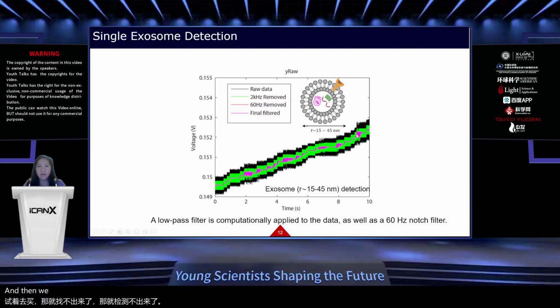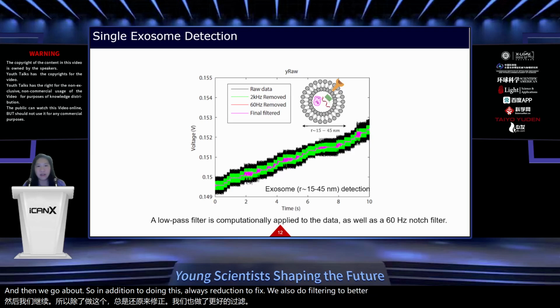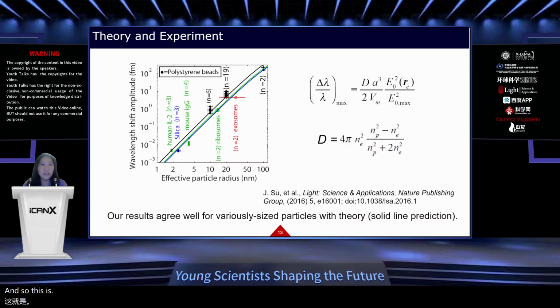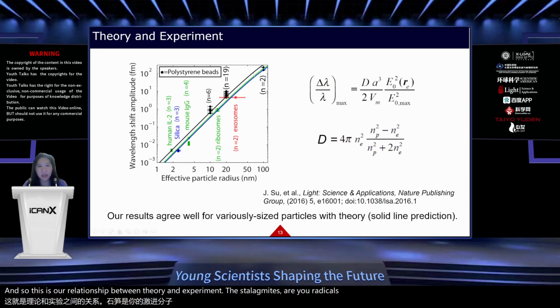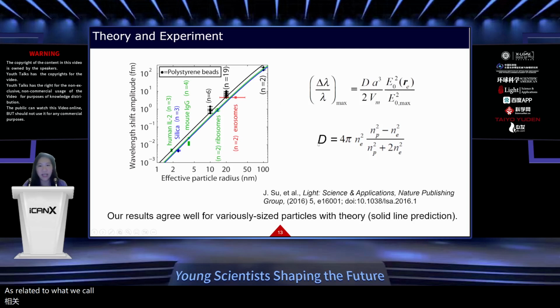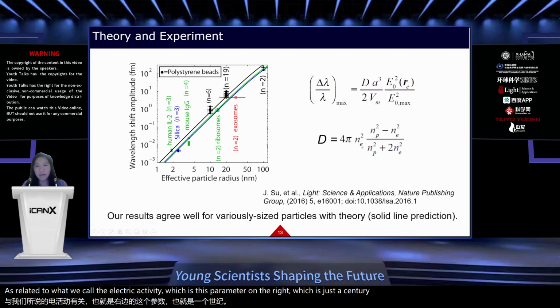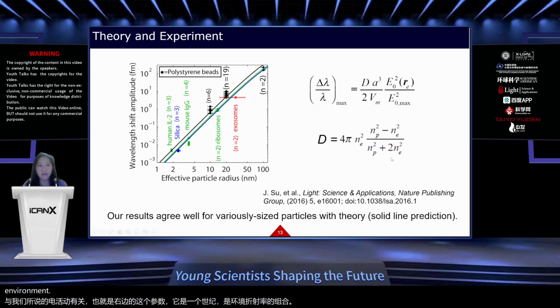And then we do a low-pass filter on our data. So in addition to doing these noise reduction techniques, we also do filtering to better enhance our signal. And so this is our relationship between theory and experiment. The solid lines are theoretical predictions, as related to what we call a dielectric factor D, which is this parameter on the right, which is essentially a combination of the index of refraction of your environment and the index of refraction of your particle.